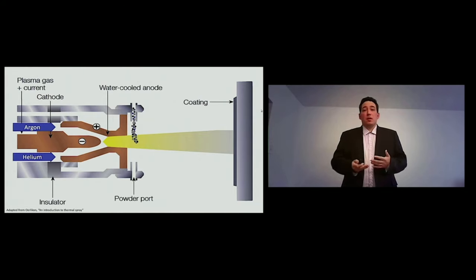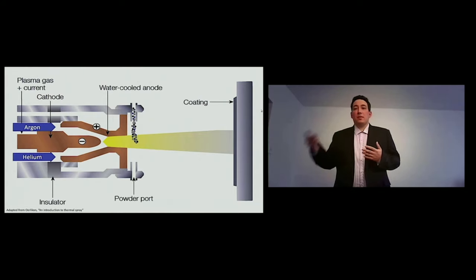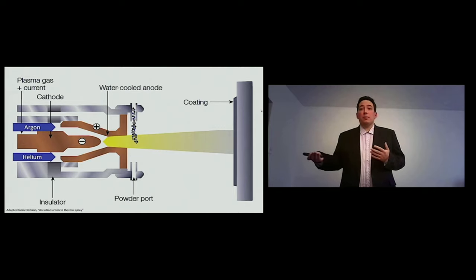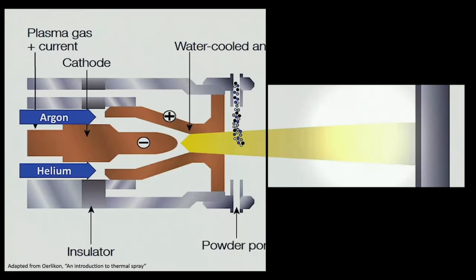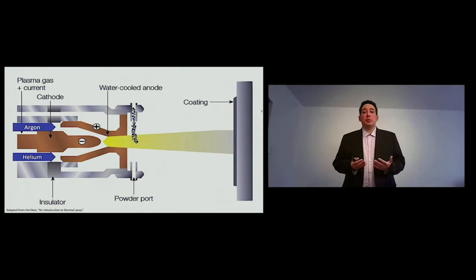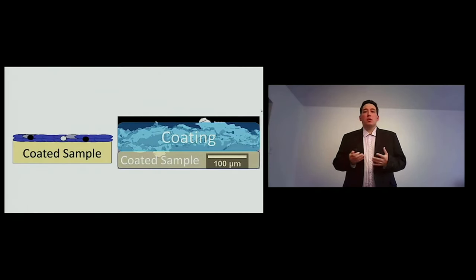These melted particles are accelerated towards the coating or the surface that we want to protect, building up the coating. Well, we actually did that. By using this technique, we produce a coating using data from literature for the parameters of spray or deposition. This is what we got. So what you see in the top part is the coating, and the bottom, the coated sample.